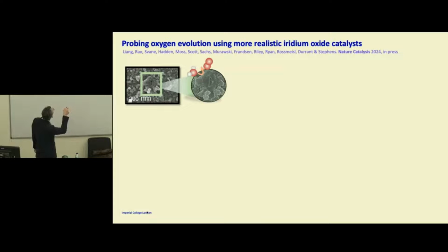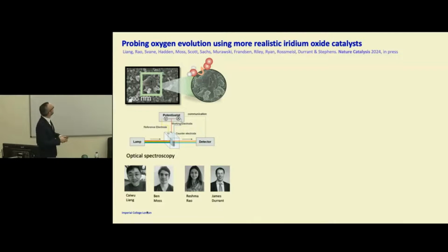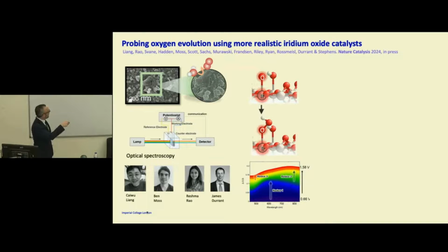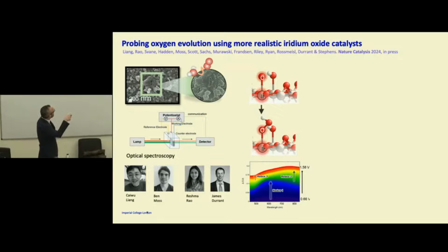You can see that this is a microscopy image, and they're quite rough. So luckily, I'm partnered up with James Durrant, Reshma Rao, Ben Moss and Caleu Liang, a PhD student who's in the audience as well. James' group are experts at spectroscopy, basically shining a light through the sample and seeing how it changes as a function of applied potential. And so we got these really nice spectra. I won't go into detail about what they mean exactly, but what we can tell from these spectra is how strong the binding of oxygen is to the catalyst surface.